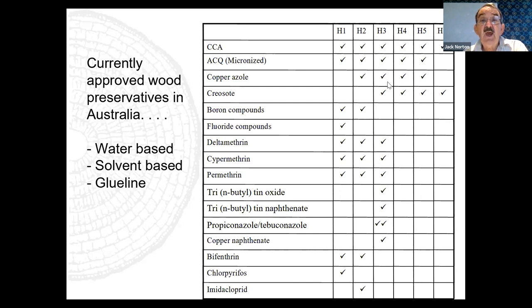CCA, ACQ, and copper azole chemically bind to the wood. They chemically react with the wood, and once they're chemically reacted, they don't wash out. Creosote dissolves in an oil, is an oil or a tar. These are also oil or tar or LOSP preservatives, and they're dissolved in organic solvent, so they're not water soluble. There are also some glue line timbers. As landscape architects, you will predominantly, I imagine, be interested in CCA, ACQ, and copper azole, because they're the ones used for landscape outside, therefore it's got to be fixed to the wood.